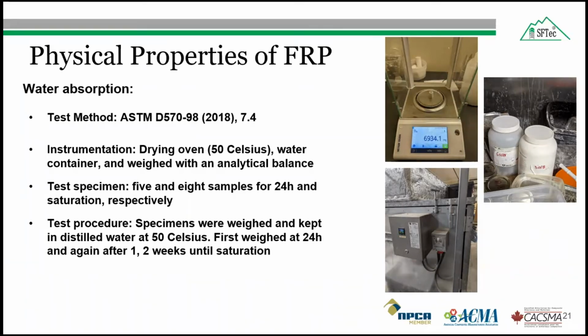And saturation was confirmed when the increase in weight over 3 consecutive measurements was less than 1%. So the water absorption at 24 hours or at saturation was calculated as the increase in weight in percentage, equal to the wet weight minus the condition weight, divided by the condition weight. The wet weight is either the weight of the bar after 24 hours or at saturation. The condition weight, which I told you earlier, is the weight after we initially dried the sample before putting it into water.